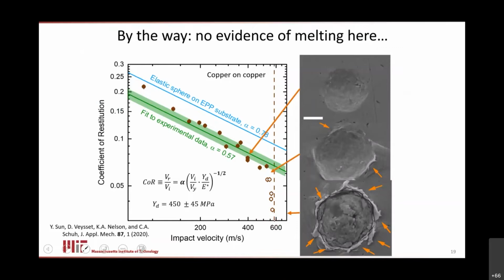So a lot of people, when they see that video of a splash, they instantly go to liquid. They imagine that some liquefaction has occurred. But I want to emphasize that this is not a melting phenomenon. So right now, I'm not talking about melting. In fact, you can do finite element simulations. You can calculate the adiabatic heat that goes in. There's definitely some heating that goes on in these experiments, but there's no reason to think we would get near the melting point of copper.